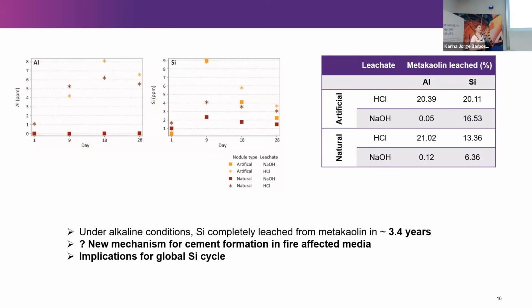So I had put together a little leaching experiment to see if this is what's happening in my samples. What I did was I took samples that had been heated and I popped them in either an alkaline solution or an acidic solution. So here the stars are HCl and the squares are sodium hydroxide. And you can see that under acidic conditions, the aluminium starts to be mobilized out of the sample into solution, but under alkaline conditions, it's quite immobile. Whereas for silica, it's roughly equally mobile under both acidic and alkaline conditions. And as it turns out, this is pretty well known in the materials industry. So I didn't make any groundbreaking discoveries here, but it's never been seen in geological samples before.